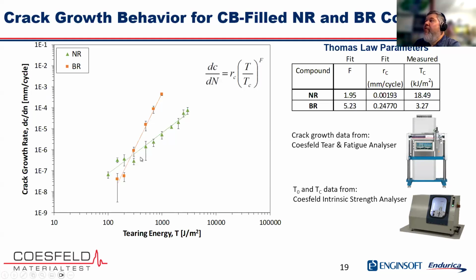The green data points are for natural rubber, and the orange data points are for a butadiene rubber. And you can see they're quite different. The butadiene rubber is a much weaker material. Like if you do a tear strength test, the butadiene is going to break first at a much lower load than the natural rubber. And you can see that as higher rates of crack growth here compared to the natural rubber. But if you keep reducing the energy input sufficiently, right, as you approach the threshold, there's a reversal.